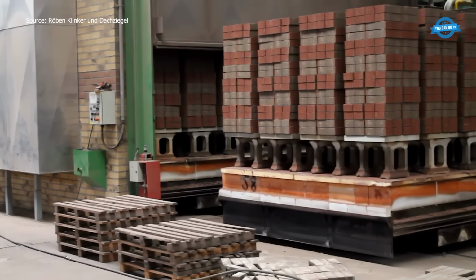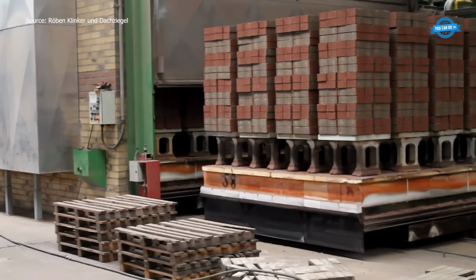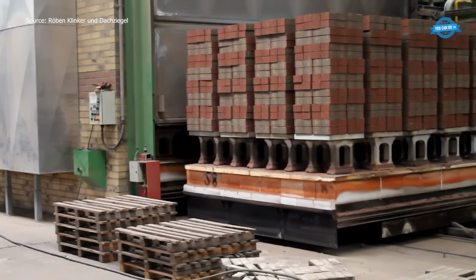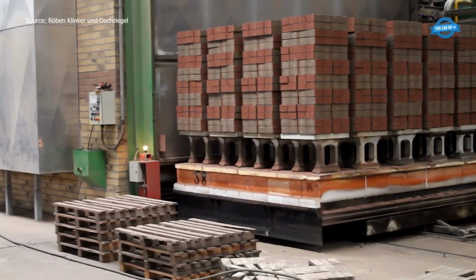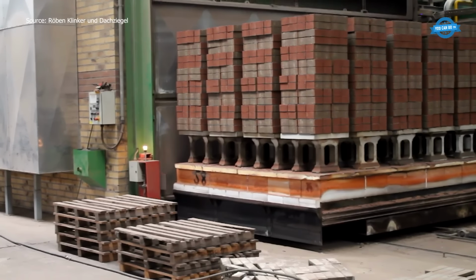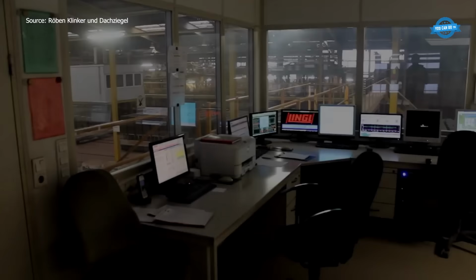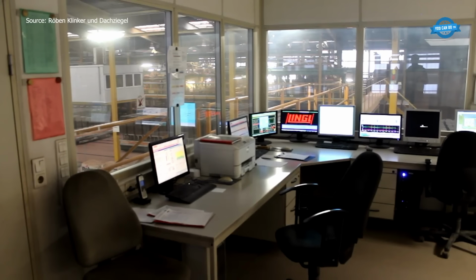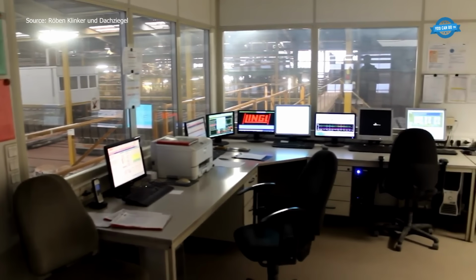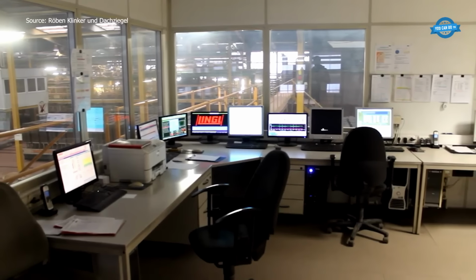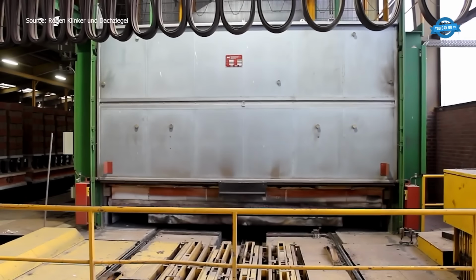Inside the kiln, temperatures rise high enough to partially vitrify the clay. This firing phase densifies the bricks, closing pores and increasing strength. Color and surface texture develop here, driven by mineral content and heat exposure. This is the point where bricks stop behaving like clay and start acting like stone. Cooling follows in stages, preventing thermal shock while locking in mechanical properties.